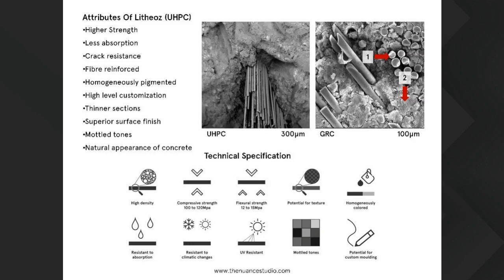It's the compressive strength, which predominantly is what talks about the strength of the concrete. The houses are built with about M20, M25 grade of concrete, which is about 20 to 25 MPa. Whereas the compressive strength of the UHPC is about 100 to 120 MPa. So it's about 5 to 6 times stronger there. The flexural strength also is very high because of the fibers. The flexing capacity really increases drastically in this kind of a concrete.